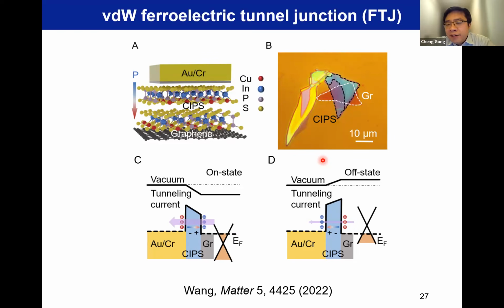But when I developed them, we found something very interesting here. It's not related to magnetism at all for this piece of work, but I'm very proud of this work. As you can see, we built a ferroelectric tunnel junction: traditional metal chromium, and 2D ferroelectric copper indium thiophosphate. In the experiment, it's about 3.5 nanometers in thickness, just about 4 layers, and then graphene as a bottom electrode. So you have an asymmetric electrode. That's the key for a ferroelectric tunnel junction.